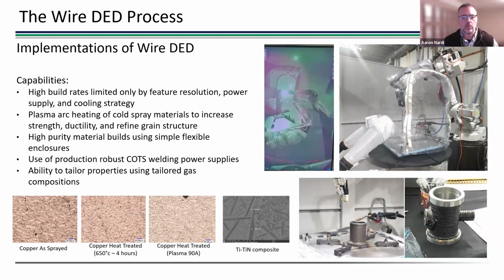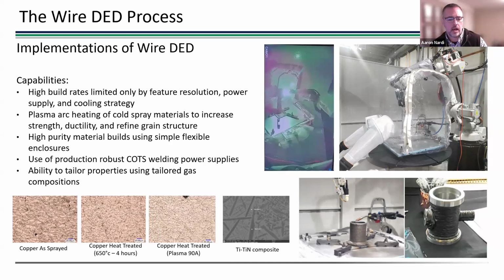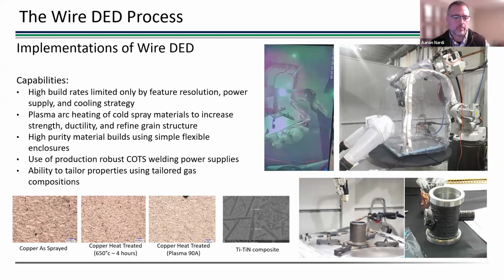So in this case, we're actually introducing another gas into the plasma process to actually try to create a composite structure in a titanium weld material. So you could see here pure titanium with titanium nitride formed within the structure of the titanium itself, hardening the material, providing wear resistance, and so forth.